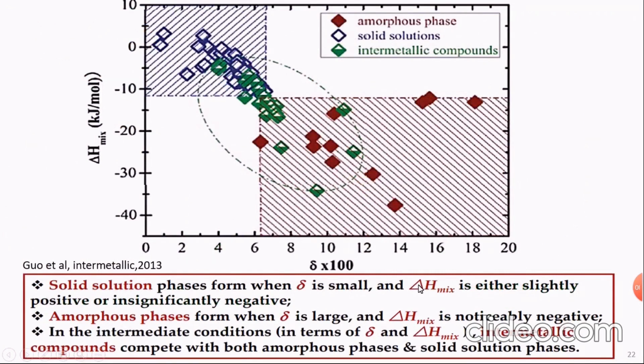Some people suggested that solid solution phases form when the atomic radius difference is small and delta H of mixing is either slightly positive or insignificantly negative. If we see this chart between the enthalpy and the atomic radius, we can see that in a certain area I can have solid solution. Otherwise, I can have amorphous phases or intermetallic phases. They said that in the intermediate condition, in terms of delta and delta H mix, intermetallic compounds compete with both amorphous phases and solid solution phases. So you have a certain area of competing between the two together. But if you keep yourself right here, you will have solid solution and you will have an ideal high entropy alloy.